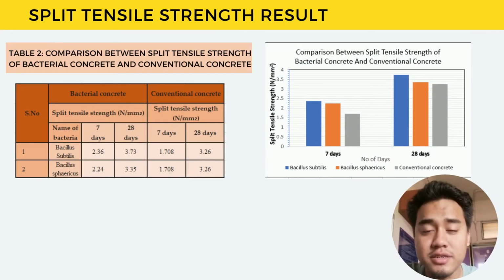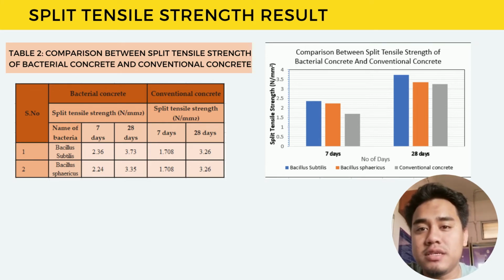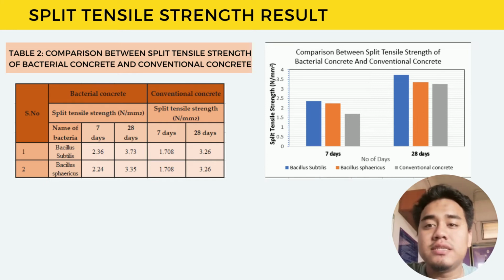Split tensile strength result. Table 2 shows the comparison between split tensile strength of bacterial concrete and conventional concrete. Two microbial materials were tested, which are Bacillus subtilis and Bacillus sphaericus, along with conventional concrete. The results showed that Bacillus subtilis has the highest split tensile strength during 7 days and 28 days of curing, which are 2.36 Newton per millimeter square and 3.73 Newton per millimeter square respectively.